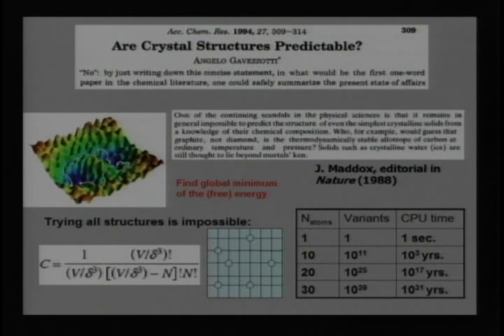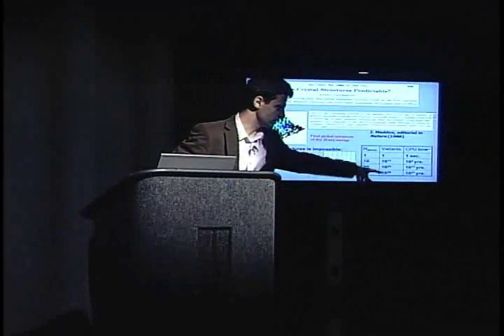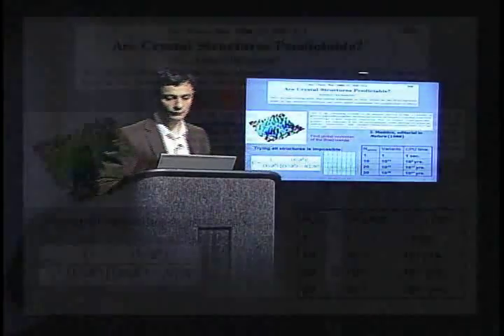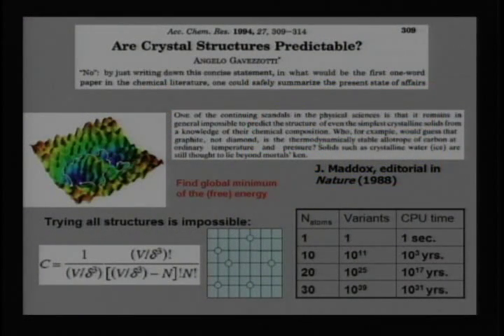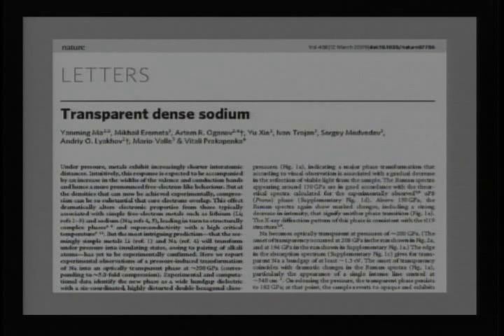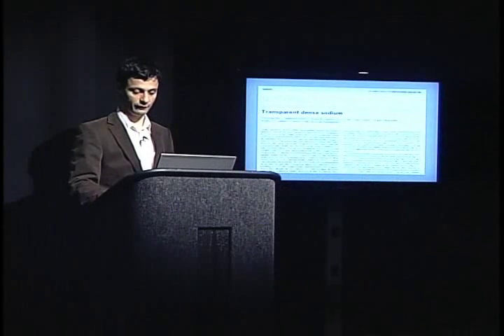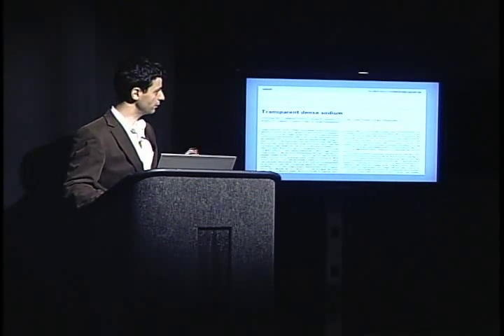The structure was predicted using our evolutionary methodology for crystal structure prediction. The thing is that until recently it was extremely difficult, often not possible, to predict the structure of a material knowing just the chemical formula. The reason is that there are so many different possibilities in which you can place atoms inside a crystal structure that the number of possibilities defeated any reasonable calculation. The number was truly astronomical. However, the method that my graduate student and I have invented solves this problem to a very large extent and allows prediction of pretty complicated crystal structures. This is the method that Yanming Ma used together with me, and he found this exciting new phase of sodium. We published a paper in Nature in March 2009 about this discovery.